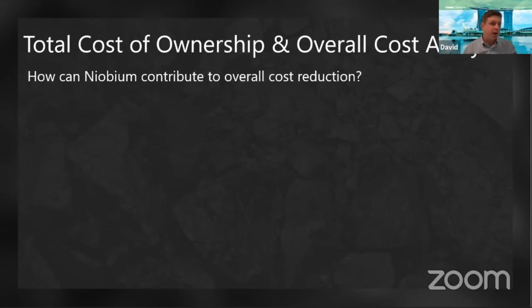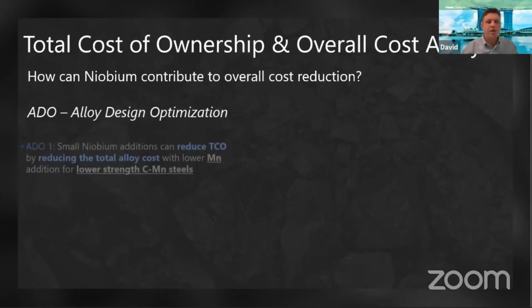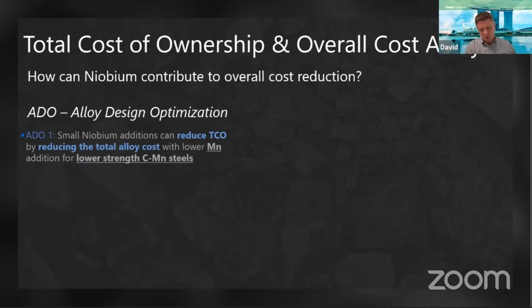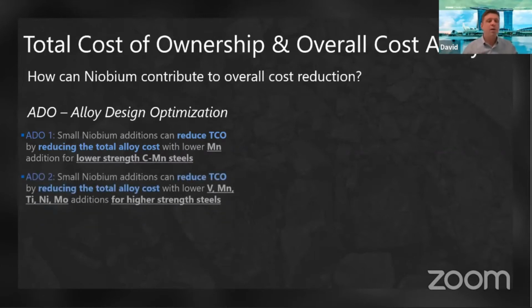We are the biggest niobium supplier and niobium technology partner in the world, so we need to find a way for niobium to do that. And as Dr. Patel just explained, we found several different ways. One of them, we call alloy design optimization, where, as was very well explained, niobium can lower the manganese addition for commodity carbon manganese grades with very small amounts, ranging from 60 to 100 ppm, for example. Or for even higher strength grades, other elements such as vanadium, manganese, chromium, titanium, nickel, molybdenum can be reduced or redistributed by a correct addition of niobium, which can change the strengthening mechanisms in a way that you can actually reduce the costs.